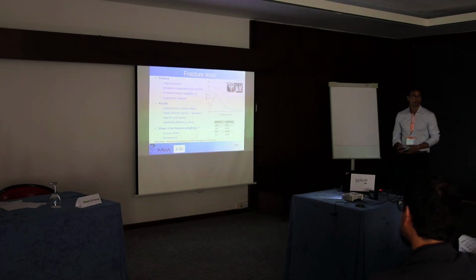Here let's comment the results. So we have one curve for each orientation. The first one, the orange one, being the crack perpendicular to the layers, and the second one, the blue one, parallel to the layers. First of all, we can see that these are very different behaviors when the crack is propagating. However, we can still note that in the first initial region here, which corresponds to the elastic regime, the behaviors are quite identical.